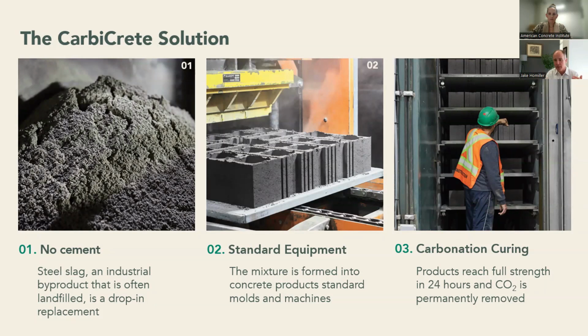So a typical cement-based concrete product goes into a curing chamber. It's time, temperature, humidity, and the material comes out partially cured, and then typically it would sit in the yard for 28 days to reach full strength or full hardness. In our process, we use a similar chamber.